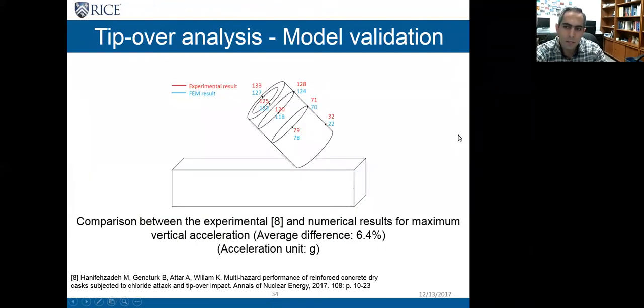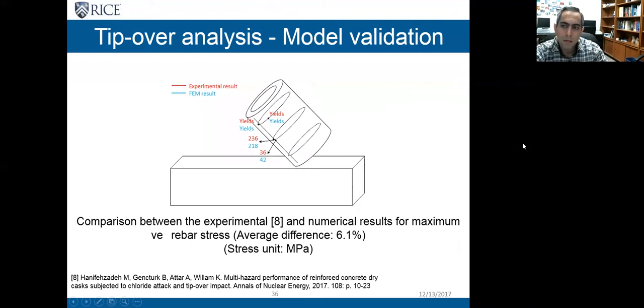Another parameter of interest in impact tests is acceleration. In this study, the researchers reported the maximum vertical acceleration. In this figure, I'm showing my results with the experimental results, and the average difference between the results is about 6%. I compared also my stress results in the rebars with the results reported from the experiment, and the average difference in this case is about 6% again.